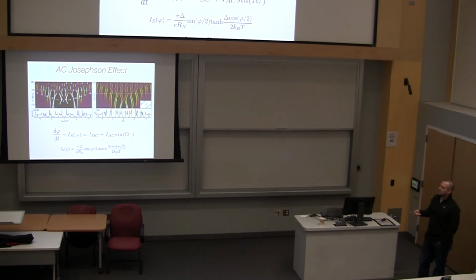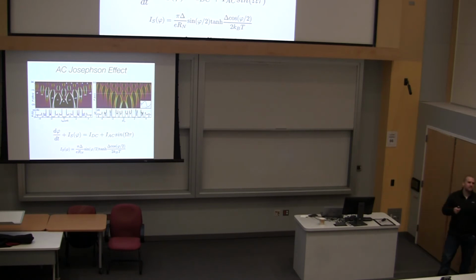Because these junctions can all be simulated using this very mechanical model of the resistively shunted junction model, we can actually simulate what's going on. So we basically simulate this equation, and what we do to change these simulations is we change the current phase relationship until we get something that gives a very good match. And what we found is that the current phase relationship which matches most closely to the data is something that's very highly skewed, which tells us there's something that's very highly transmitting in the junctions